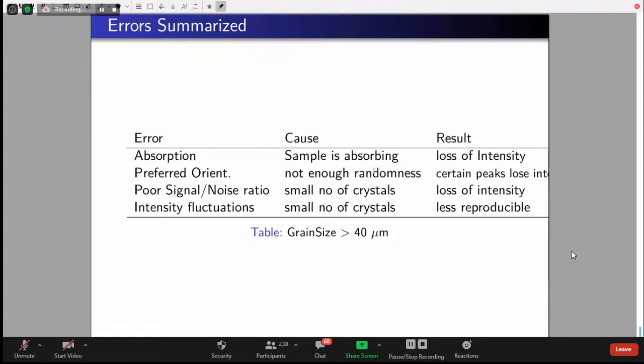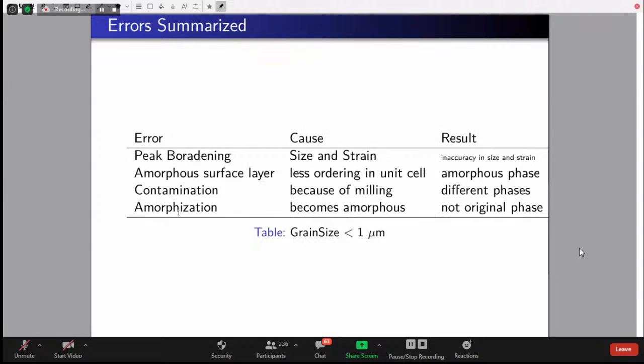Preferred orientation is where you don't have enough randomness, meaning you did not grind it properly. So certain peaks will lose their intensity. If you give a very small amount of powder to the diffractionist, then we will have a small number of crystals. Again, you will lose the intensity. All these intensity fluctuations will never be reproducible. So your interpretation is completely ambiguous. You don't have any control in your interpretation.